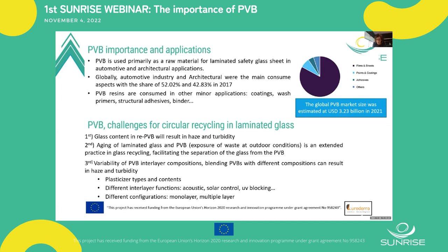These applications involve high quality properties, mainly in terms of optical properties, also mechanical, but the optical properties are the ones restricting this application. So the first challenge in this recycling is the glass content in recycled PVB. Any particle of glass or dust can result in haze in the interlayer film, so avoiding its use in optical applications. In terms of transmittance, it cannot decrease so much, but in haze, in this parameter, there is some limitation.